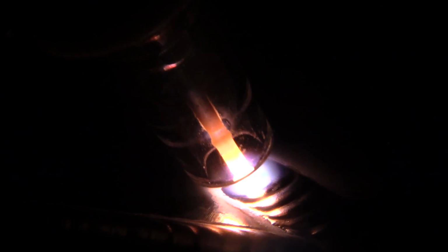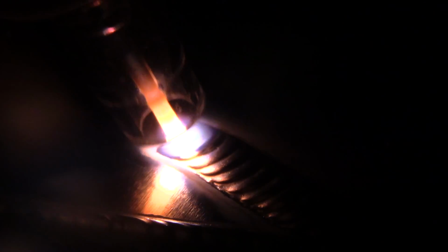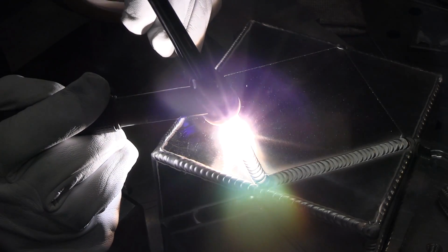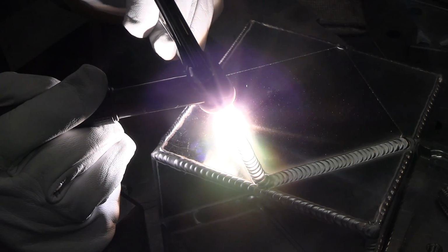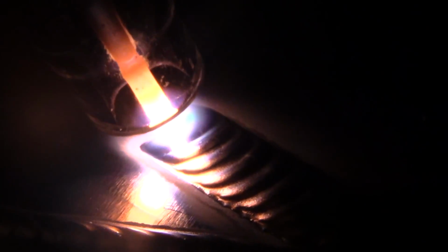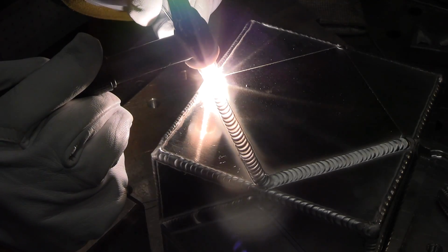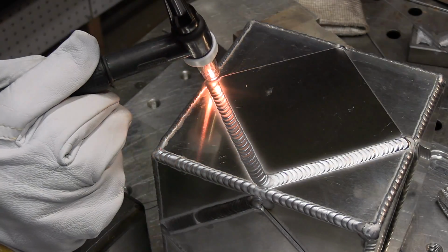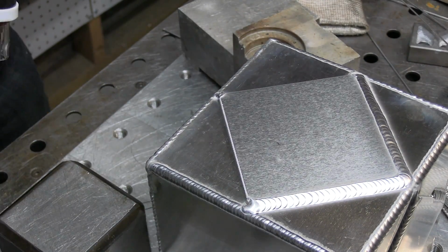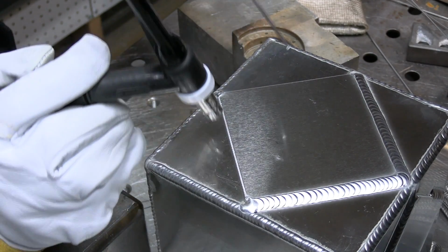Here's a shot of a start of a weld, looking through the cup almost at where I'm feeding wire. Another benefit of a clear cup: you don't always need that, but sometimes it's very helpful to be able to look through the cup. If you pay attention here, you might notice me raising and lowering the torch. I've shown this several times before, but basically I'm just using a really tight arc when I'm trying to push that metal into the root, and then raising as I feed the rod and the puddle grows in height so that I don't clean electrodes all day long. I'm pretty good at dipping an electrode, so that little technique has proved useful for me.